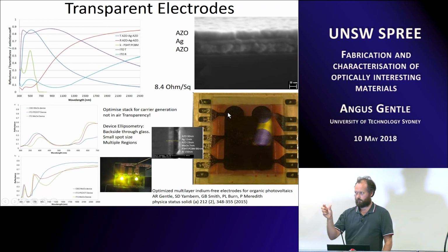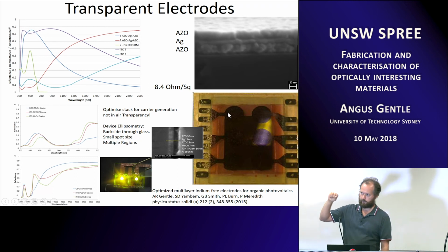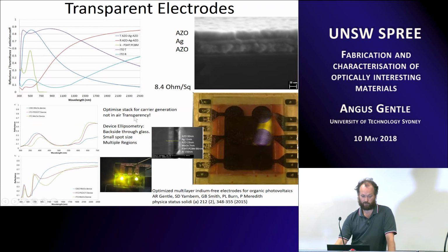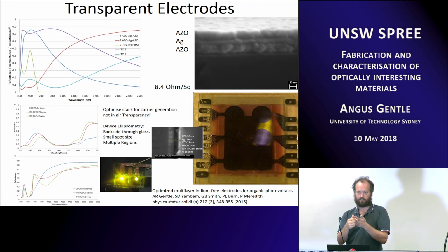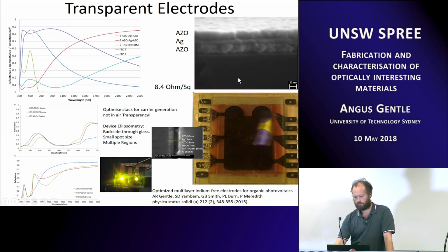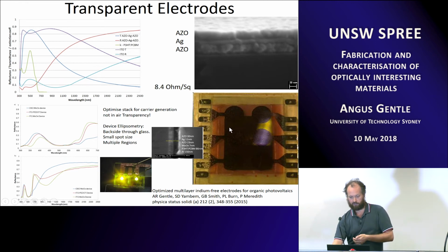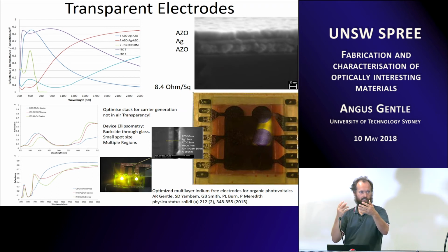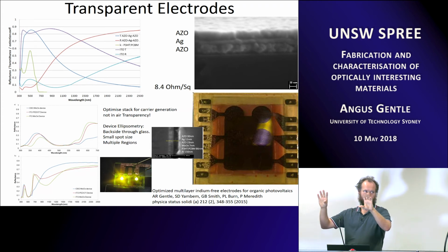These are the 1-inch square slides, so you've got this small little dot on them. If you want to look at how much light actually gets absorbed by the cell, we're doing ellipsometry on the little pad. If you ever do ellipsometry and want to know exactly what's going on, you don't want a single sample, you want the sample in a couple of different scenarios. In this case, you can have an aluminium back reflector in there, or you measure and model it in the other part where you don't have the back contact. Then you have two different measurements of the same part of the material, link the model in WVASE, and try to get the exact thicknesses out of a multi-layer stack.